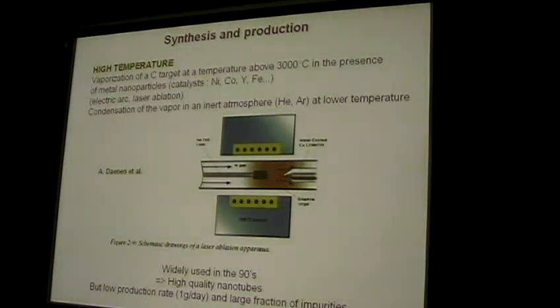Here are some examples. Carbon nanotubes cannot normally be dissolved, but you can modify them. A colleague in Bordeaux reduced carbon nanotubes by addition of cations — for example lithium or potassium — making a nanotube salt such as lithium, with one lithium ion per a certain number of carbon atoms. This salt, in a polar solvent, can be dissolved. In the video, my colleague Alain Penicaud is adding a droplet of a polar organic solvent on top of this nanotube salt, and you observe the spontaneous dissolution of the carbon nanotubes — completely impossible without reducing the carbon nanotubes first.